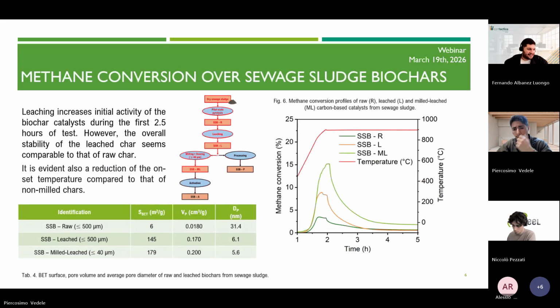So let's speak about the first 3 biochars: the raw, the leached, and the milled-leached. In particular, as you can see, the leaching increases the methane conversion. All the tests were conducted at 900 Celsius degrees, by the way. The leaching increases the methane conversion and also changes the onset temperature of the reaction.